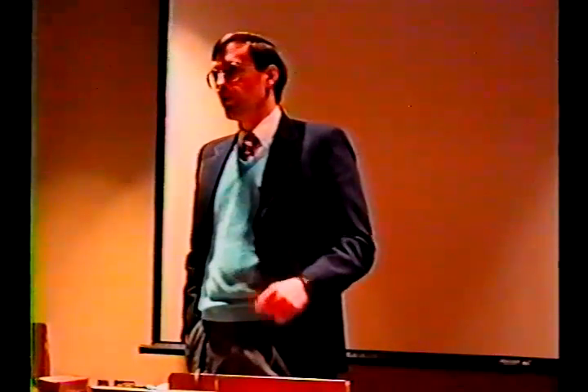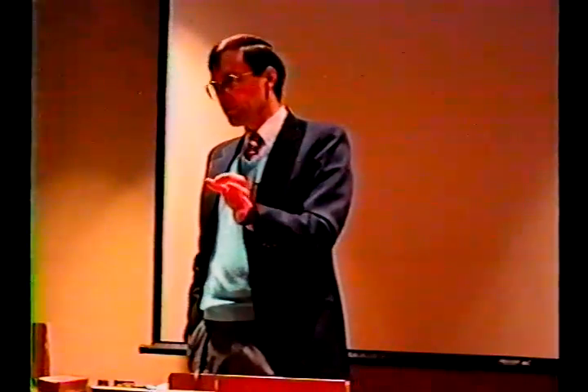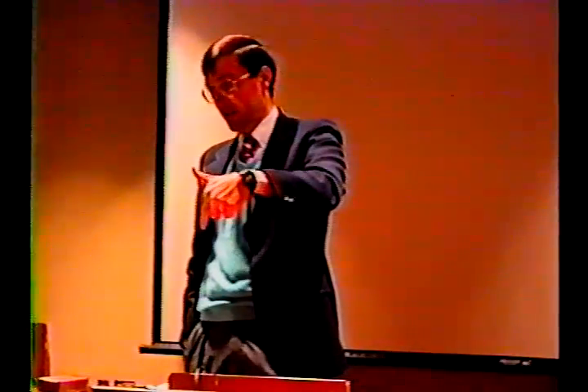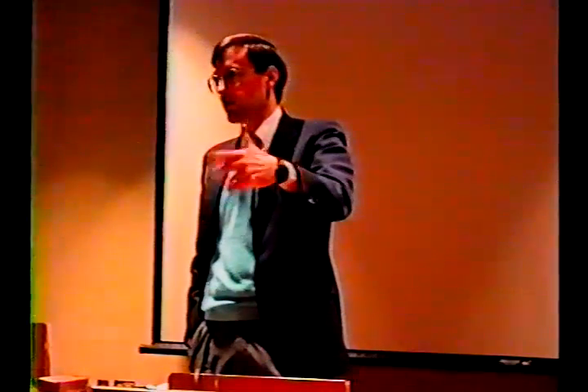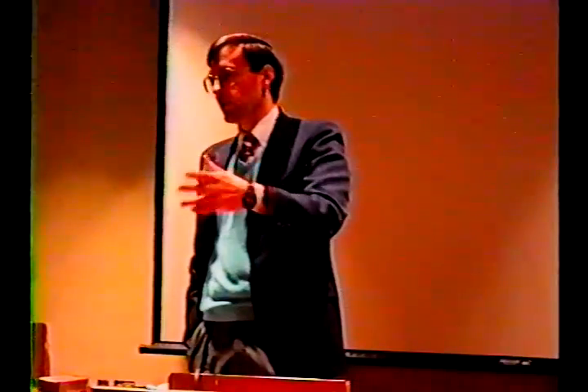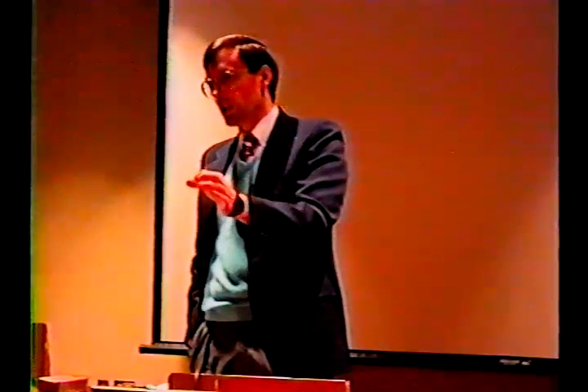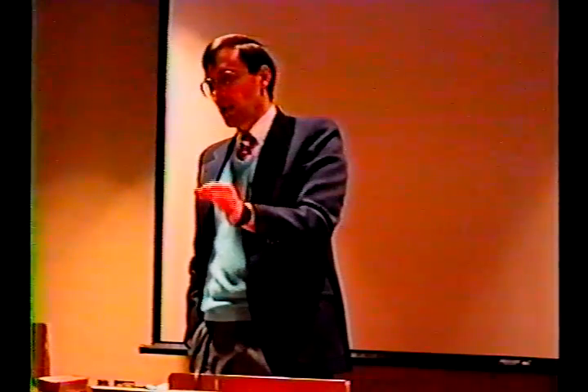But what we're doing is measuring the power and the temperature. We're blowing liquid nitrogen gas on the outside of that tube to try to cool it at the same time. That's one of the key things, so you don't get sintering and aggregation. So that's our key thing. It's not in the literature, and we hope to put it in the literature soon, to keep the particle size small.